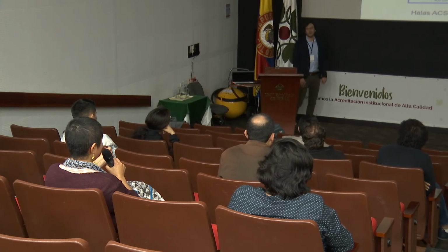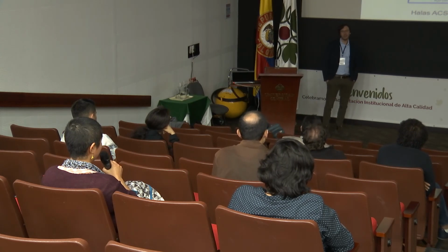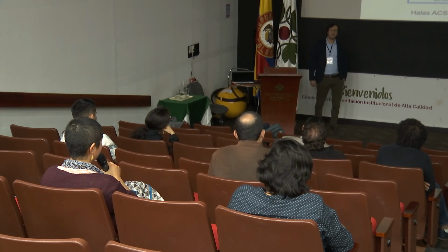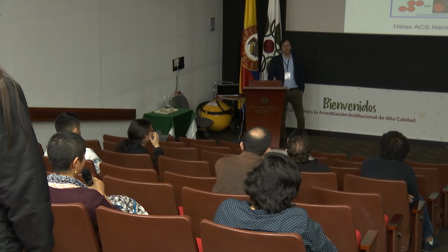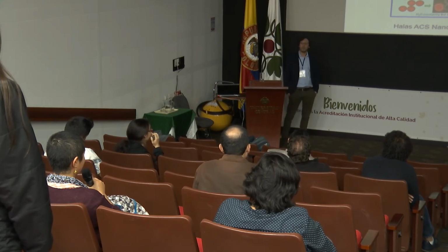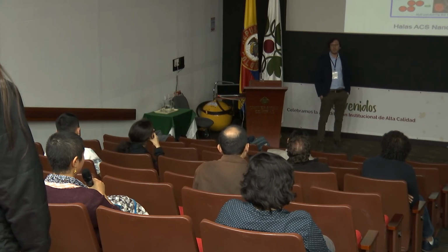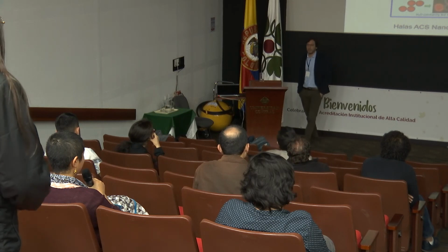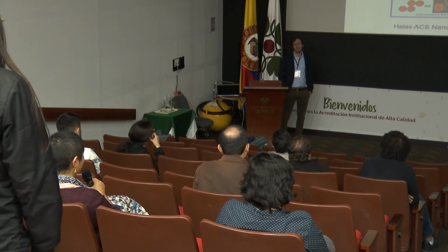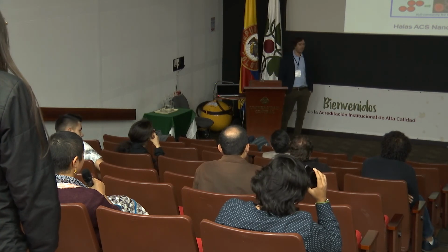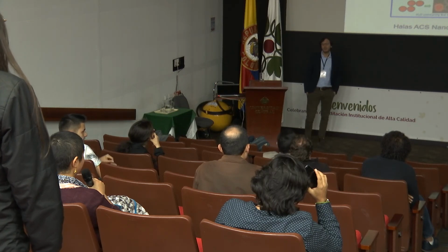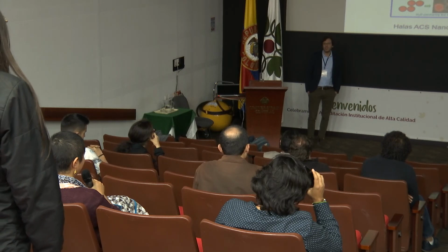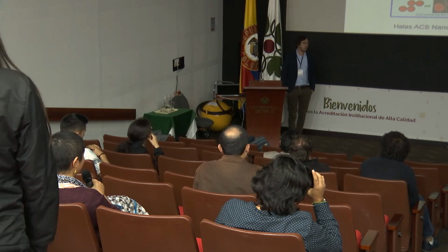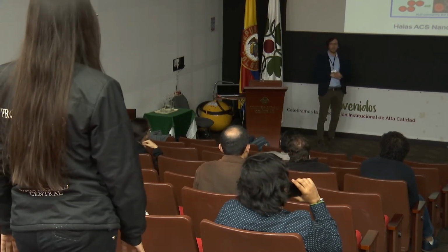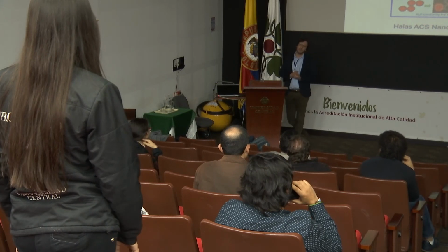Actually, we use antennas to generate heat. Plasmonic materials historically started to be used in nano optics, for communication and so on. But the problem is that they have very high losses, and also they are not compatible with the normal semiconductor industry. So people started to look at different materials like dielectrics. On the other side, people working with plasmonic materials started to look at the losses of the material. So basically they transform the losses into gain and think how to use these losses for different applications. So this is, again, a plasmonic antenna, but we don't care anymore about the quality of the resonance, we care more about what happens after the dissipation of the plasmons.